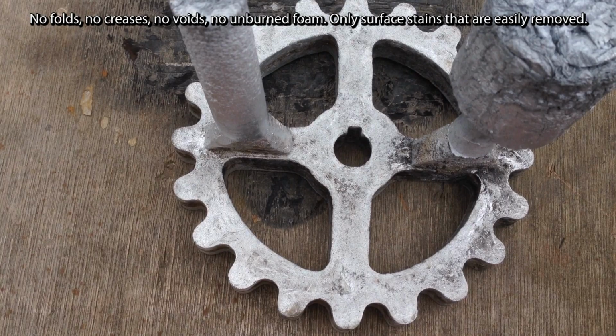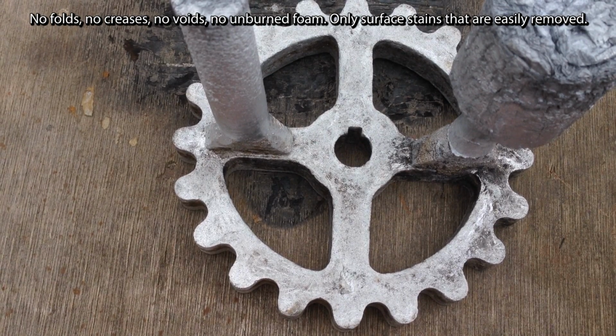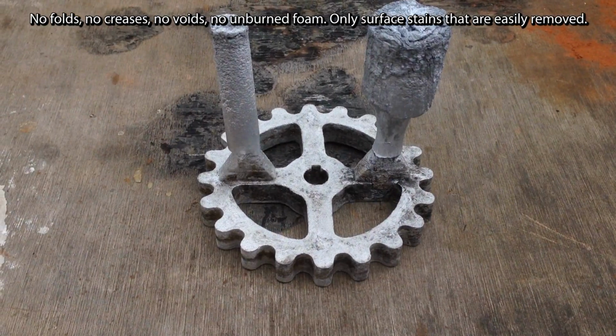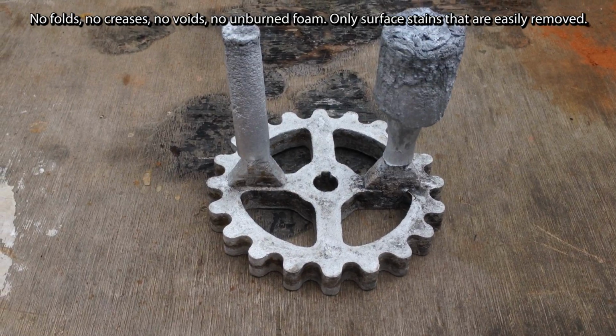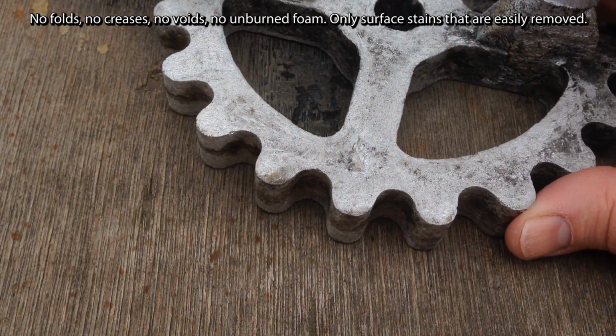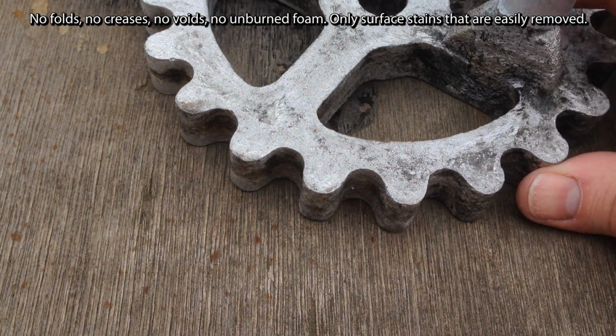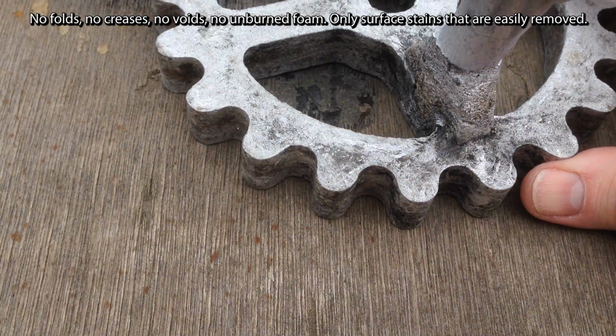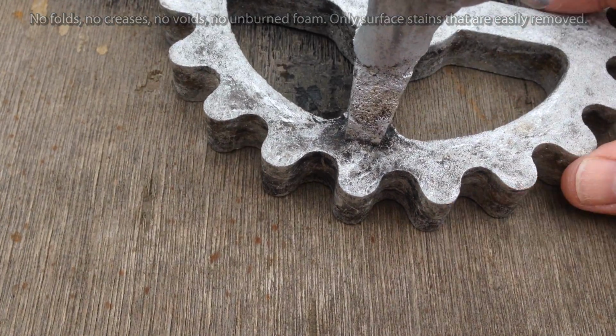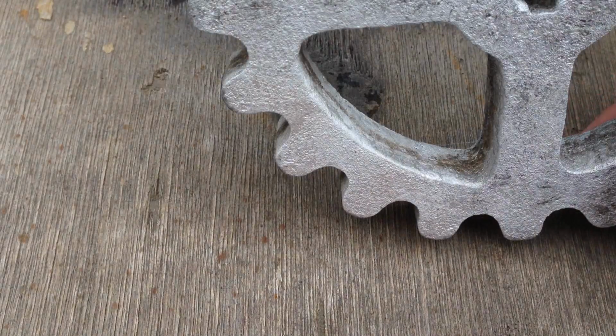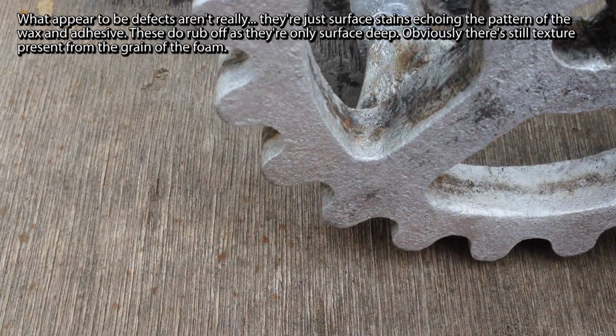And here's the result. At a glance you might think you're seeing defects, but the only imperfections in this metal sprocket are those that were present in the foam pattern. It really is as perfect a pour as I could have hoped for. A lot of the apparent imperfections are just marks created by the process, mostly in the areas where the candle wax and glue were present.